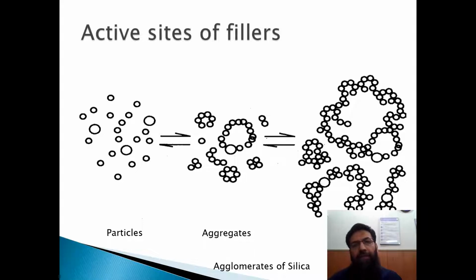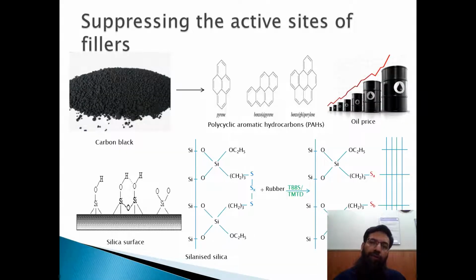So when we talk about the presence of active sites, in silica the active sites are more detrimental as compared to carbon black. The presence of active sites like the silanol or hydroxyl group on the surface of silica would actually restrict the silica from the reinforcement mechanism. So unless we remove or overcome these active sites, we can't get better reinforcement in the silica. So to have better interaction in the silica compounds, we have to treat the surface of silica with different chemicals. Mainly they are different types of silanes that are available.